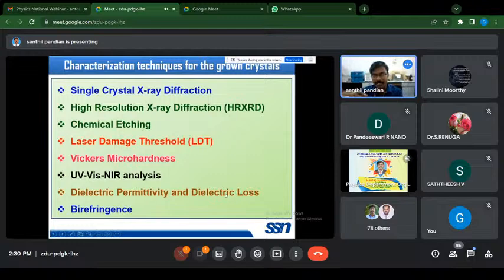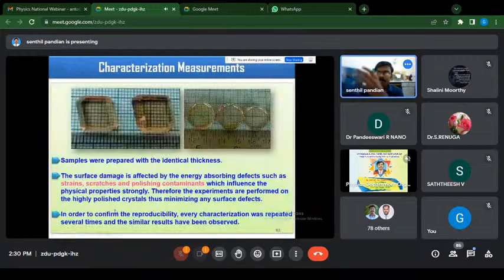For optical quality, UV-NIR. For electrical measurement, dielectric permittivity and dielectric loss, and we also carried out the photoconductivity measurement, dark and photocurrent measurement. In order to identify the uniformity of the grown crystals, we carried out the birefringence measurement.